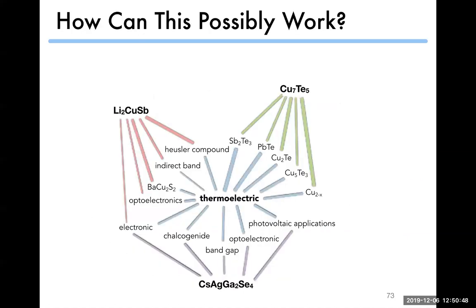So we wanted to know how this could work, right? This is a really interesting result, and we wanted to investigate what the model is actually doing to make these predictions. Is this reasonable? One way you could do this is just look at the predictions it's making, and then plot the words that are most similar to both thermoelectric and that word. So in this plot, the thicker the line, the more similar those two words are according to the model.